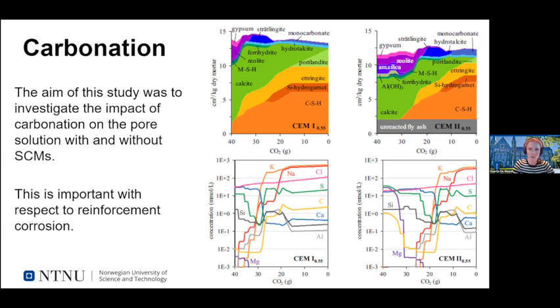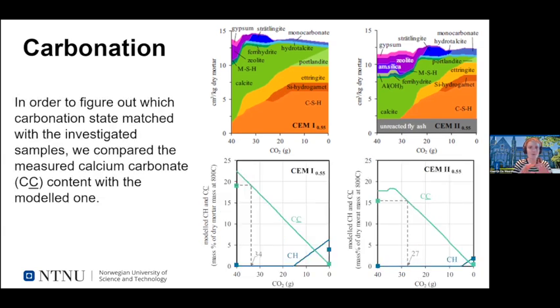Because we combine this with experiments, in order to know which phase assemblage we approximately had in our fully carbonated mortar, we matched the carbonation state in our experimentally exposed samples to the calcium carbonate level which was modeled. The modeled calcium carbonate level is the green line. We had measured in our fully carbonated mortar a level of about 20% calcium carbonate. So our fully carbonated mortars were equivalent to the phase assemblage at about 34 grams CO2.